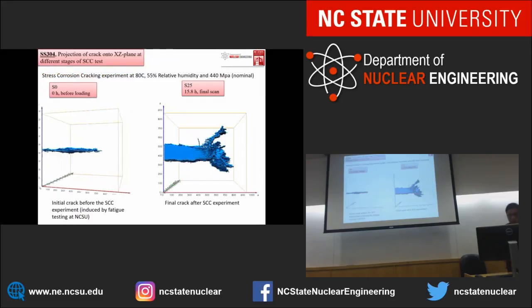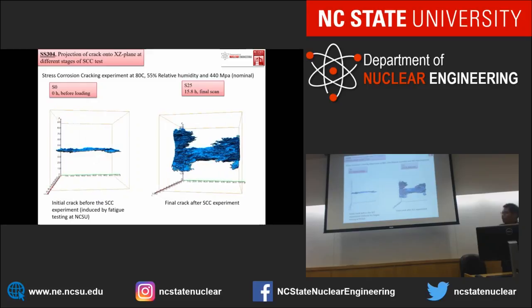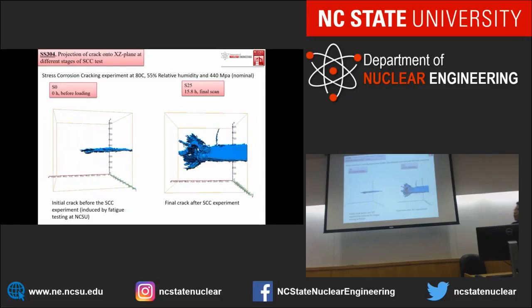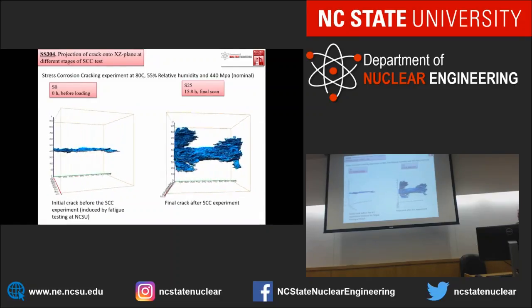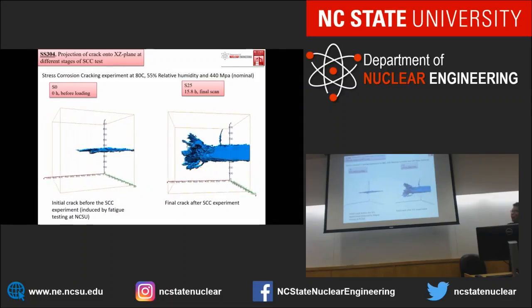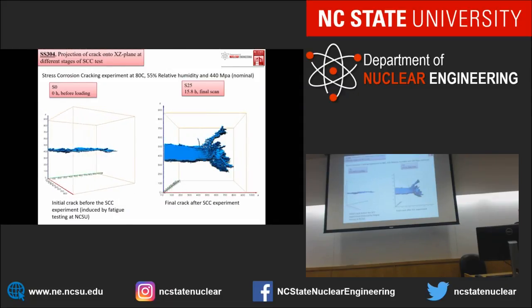And if you compare the shape of the crack before and after the experiment, we can figure out that the crack finally opened up and created some branches of small cracks due to the stress corrosion.